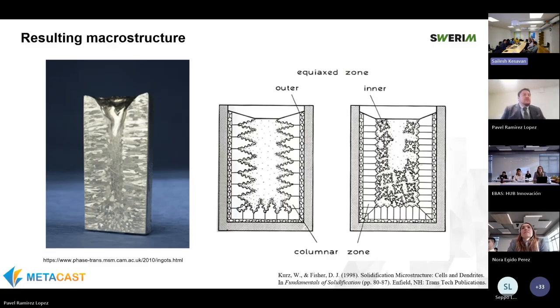Another couple of definitions which are interesting for you to have: most of the time, when we start the solidification, it occurs from the walls. They act as the starting point for solidification because it's obviously our coldest point in the ingot, and the growth occurs towards the center of the ingot, in the form of clear columns, therefore called the columnar zone. Once we achieve a certain length of solidification, there is often a transition, although it may be possible that we just have columnar grains all the way. Very often there's a transition where we start nucleating in the center, and this creates an equiaxed zone where we have dendrites growing in the center of the ingot. We will also go through the transition zone, which is called the columnar to equiaxed transition.